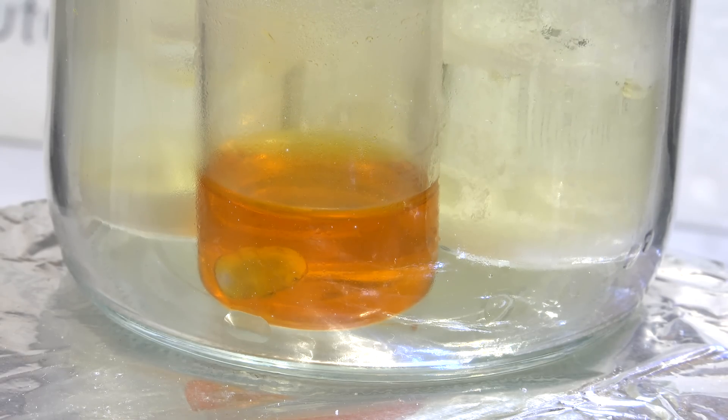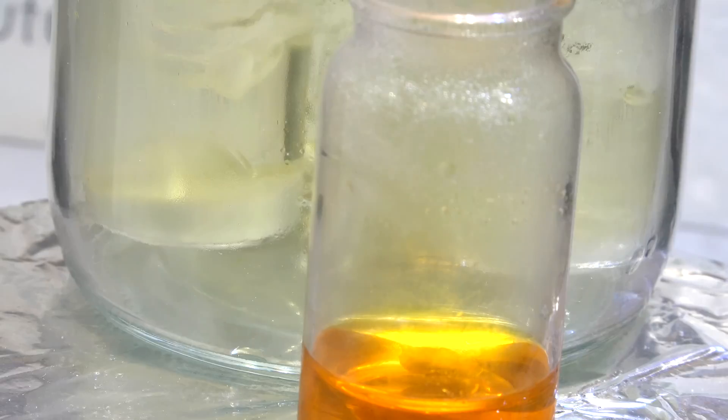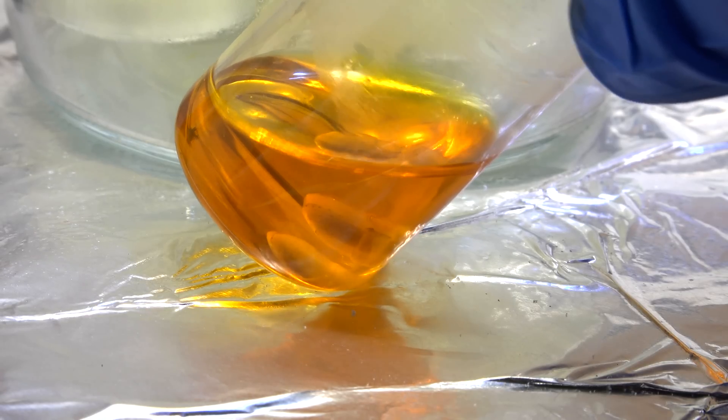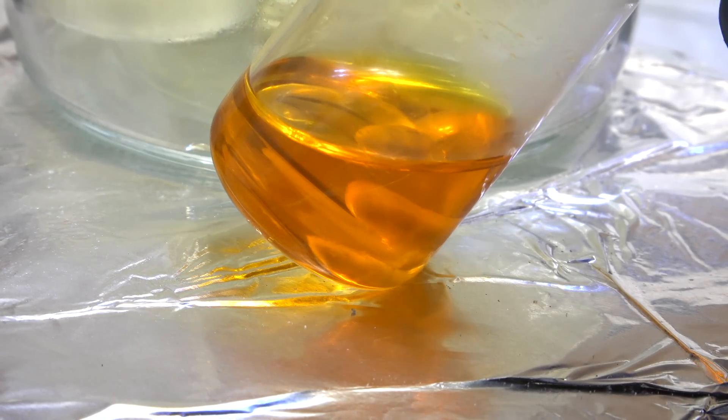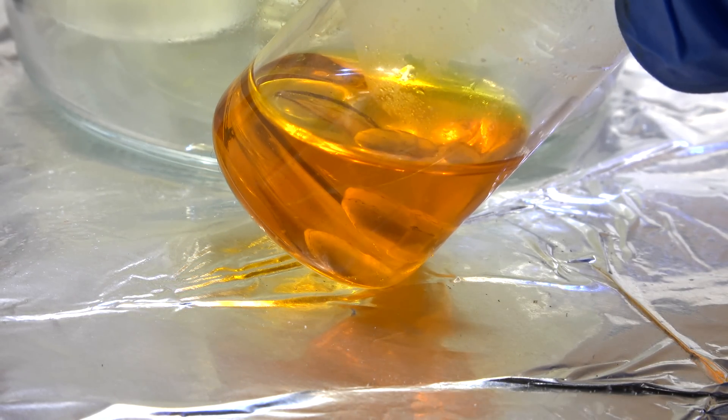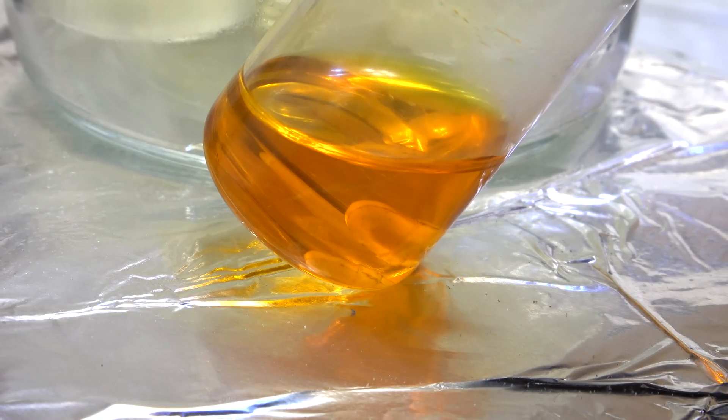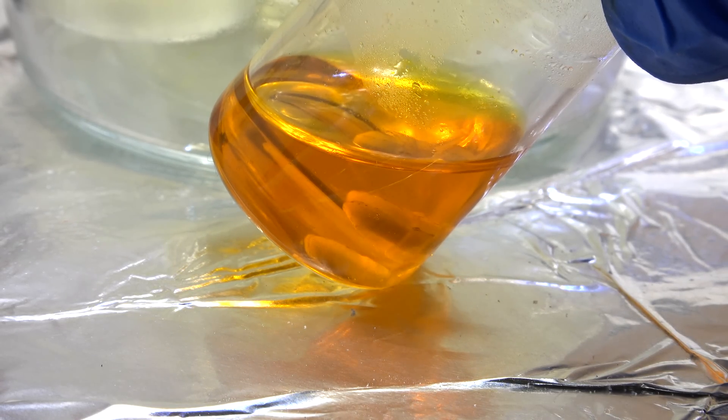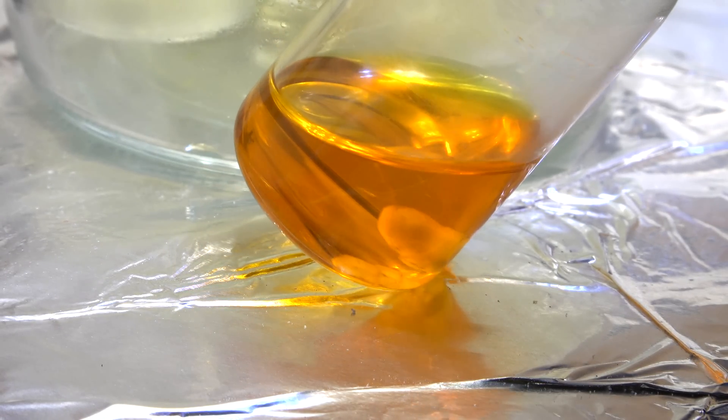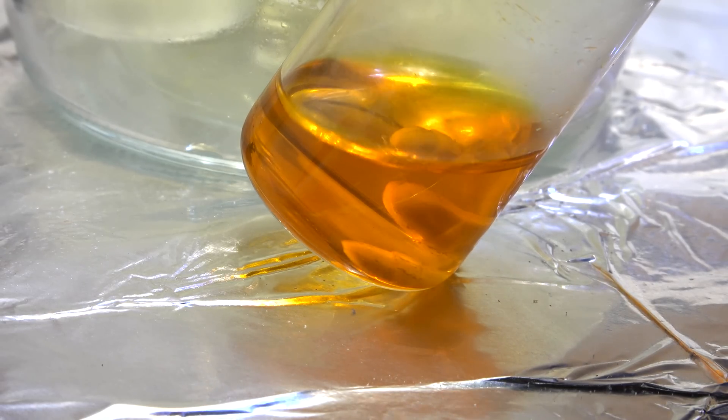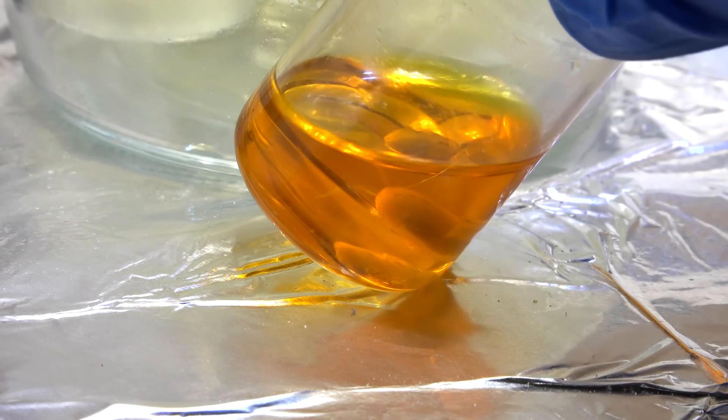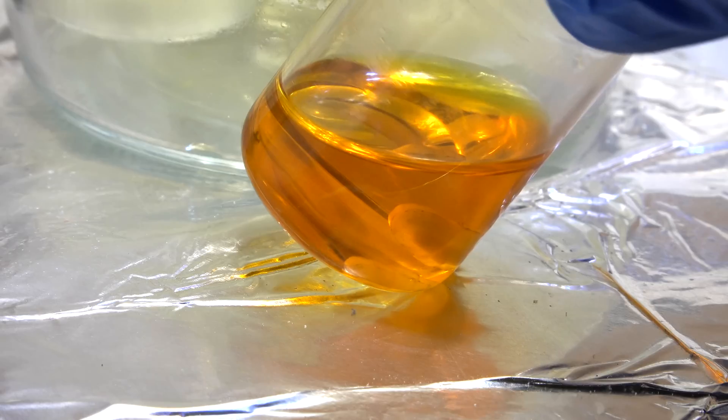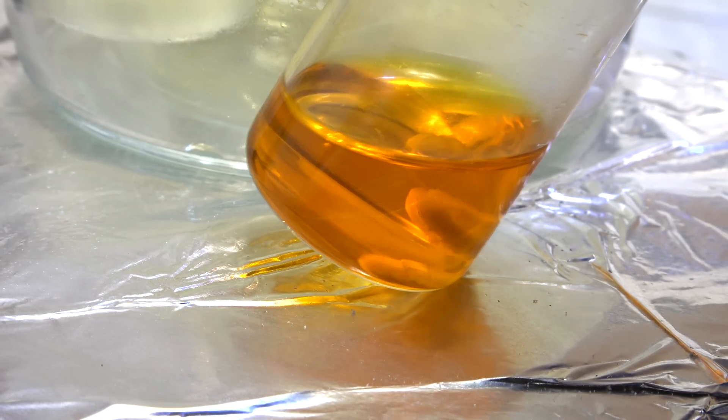Anyway, here we are a few hours later and all the platinum has dissolved. This was much faster than dissolving our platinum bar because we're using fine powder with high surface area. Chlorine gas isn't particularly faster than nitric acid. We now have a relatively pure solution of hexachloroplatinic acid. There's also hydrochloric acid but for my purposes I can use this as is. If you need to remove the hydrochloric acid you can easily boil, evaporate or distill it off. Anyway, that's how you dissolve platinum with chlorine gas and hydrochloric acid. Thanks for watching.